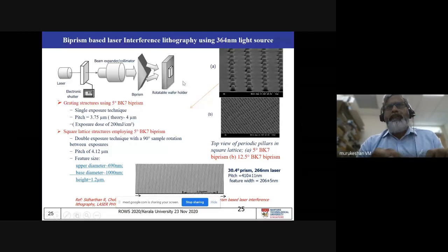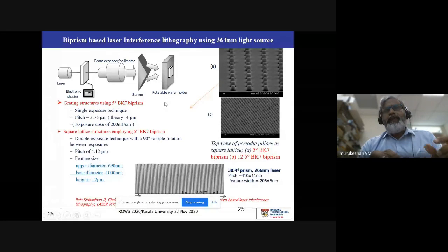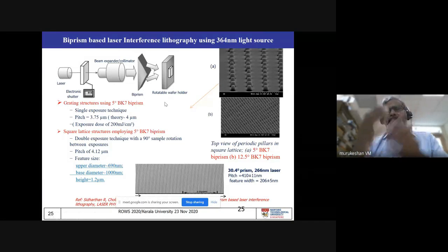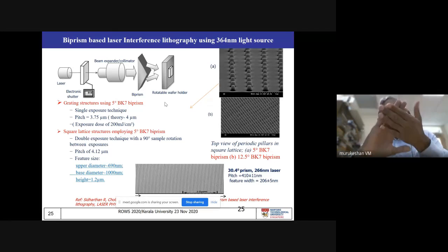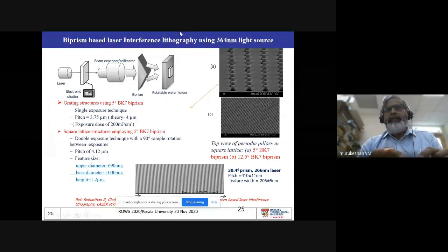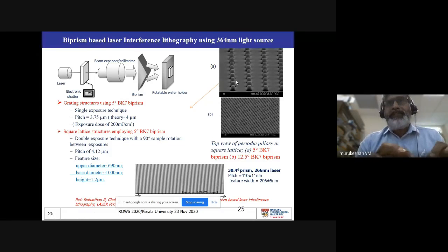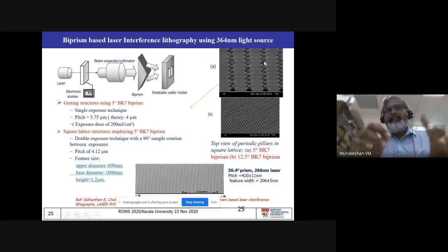If you take one line feature and rotate the wafer by 90 degrees, or certain different degrees, and expose again, you are going to cross these two patterns, and you will get pillar-like patterns or this kind of patterns. All these patterns are very good for photonic crystal applications. You fill PDMS between the structures, and you can get a very nice photonic crystal. Such applications can also be used. We use it for making a polarization splitter, a device based on that.